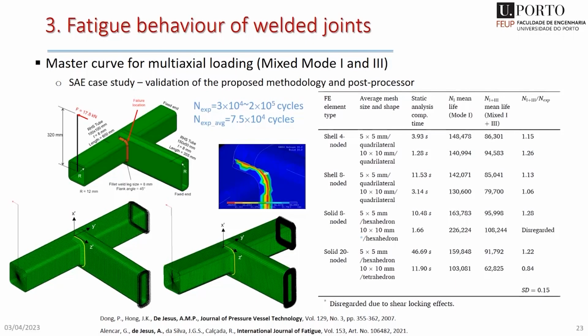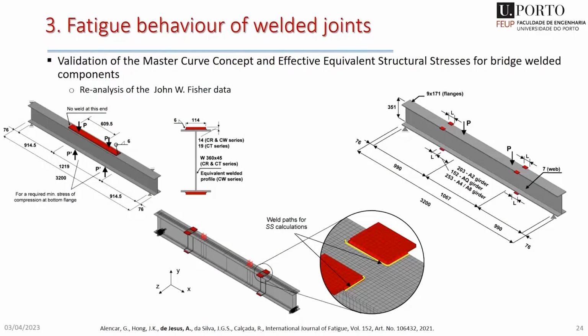And then we moved to the bridge components. So the idea is to apply this technique in welded bridges, but since we cannot test the bridges till failure, we must rely on laboratory specimens. So we went to the literature and we found a very nice, valuable database from John Fisher from Lehigh University. This data was the basis for the current design codes, European and American design codes for the welded joints.